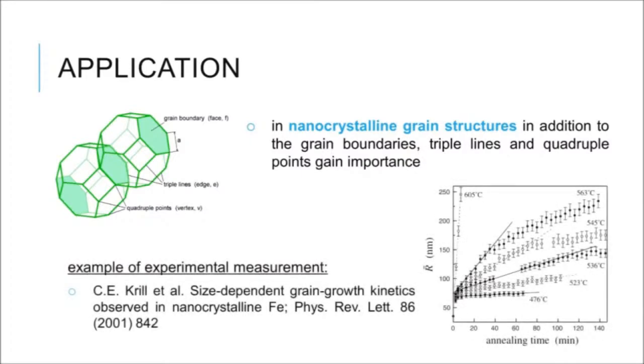Hence, you can see here an example of an experimental measurement where the average grain radius has been plotted as a function of annealing time for nanocrystalline iron. And what you see is that, apparently after a very short initial period of time, there is a linear relation between average grain radius and annealing time.